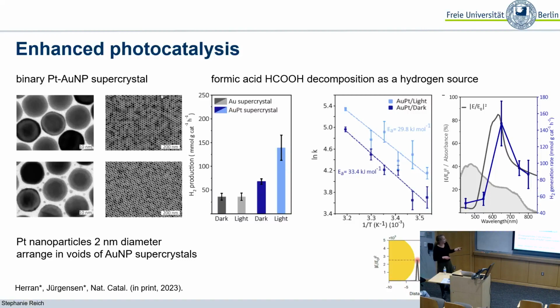Yeah? And then here's a gold nanoparticle supercrystal, or it's actually a monolayer only, where there are 2 nanometer platinum nanoparticles in the voids of the supercrystal. And platinum is a known catalyst for this type of reaction. So already in the dark, you can see that the reaction yield increased by a factor of 2. And then when we switch on the light, there is a further very strong increase in reaction.